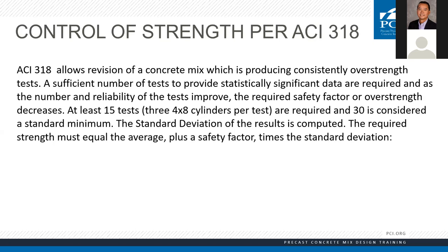This is important information per ACI 318, our design code. This allows for the revision or optimizing of a concrete mix. If you have one already, you can revise it. As long as it's proving consistently over strength tests, we can optimize that mix. We need a sufficient number of tests, then we figure out the statistically significant data showing our standard deviation and the reliability of our mix. We need at least 15 test points; 30 is recommended and considered the standard. A test point using four-by-eight cylinders means ACI 318 requires an average of three cylinders to get your 28-day test point.